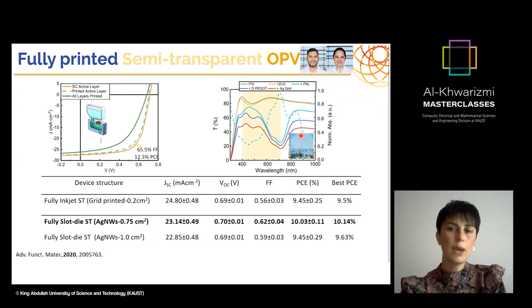So this was quite impressive, because if you looked at the transmission of this whole stack and also the single ones, you start with around, let's say, 80 to 90% when there is no photoactive layer and just ITO and zinc oxide. And when we add our photoactive layer, we were achieving almost 80% transmission. And even in the whole stack, we were reaching 50%. So this device was actually very, very semi-transparent.